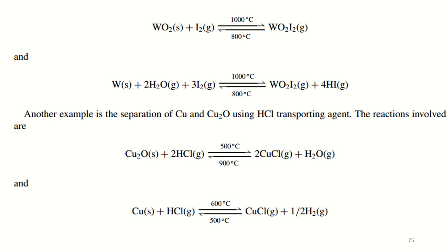Since CuCl forms exothermically from cuprous oxide and endothermically from copper, Cu2O is redeposited at higher temperature and elemental copper at lower temperature.